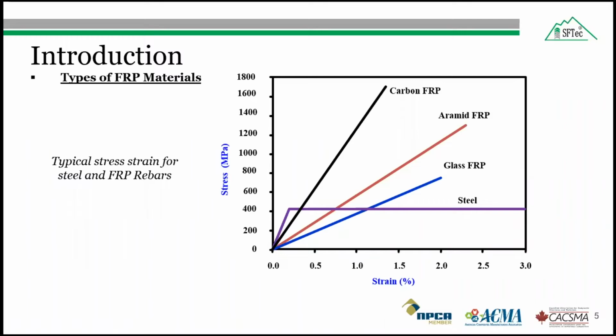Two points should be noted from this plot. First, the glass fiber reinforced polymer bar has lower strength compared to the other fiber reinforced polymer bars. Second, the strength of all the FRP bars is higher than the steel bar. However, their behavior is linearly elastic up to failure.